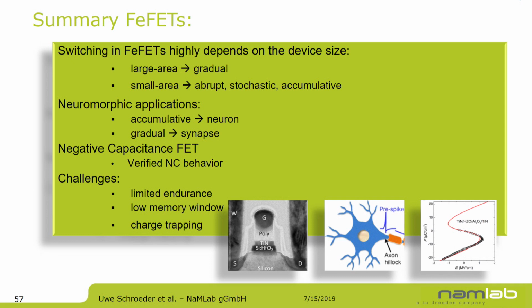Then I could show you that we verified the negative capacitance behavior in the FeFET structure. But looking at the FeFET overall, the main challenges are the low endurance currently, and here one needs to improve the defects, I guess, in the film, to improve the limited endurance behavior we have, and this is mainly caused by charge trapping.